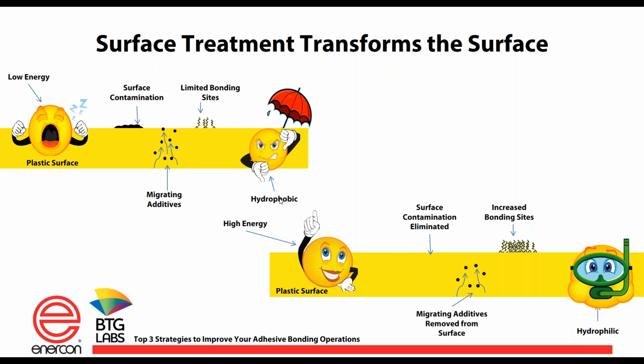After treatment, after cleaning and surface activation, we have a much more hydrophilic surface. We have increased bonding sites. If there are migrating additives on the surface, we remove those, and hopefully we've removed all the contamination, and this gives us a better surface with which to bond.